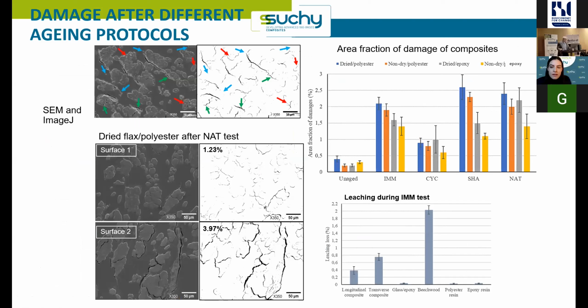Let me first show you a little bit of our damage research, of course. Here you see in this graph the damage that we could measure in micro CT scans and these kinds of tools. So the unaged, obviously very low damage, and then after immersion testing, quite some damage, which was corresponding more to what we saw outdoors. And in cyclic loading, clearly less damage than in the other aging protocols.